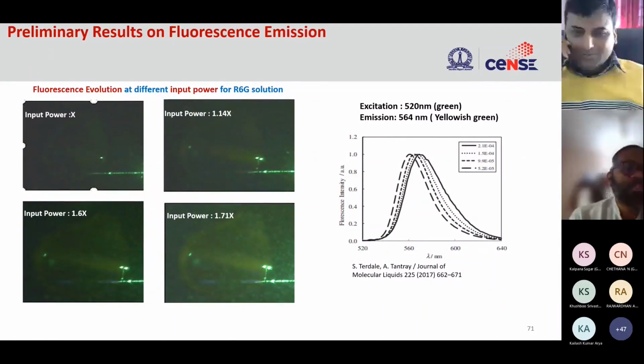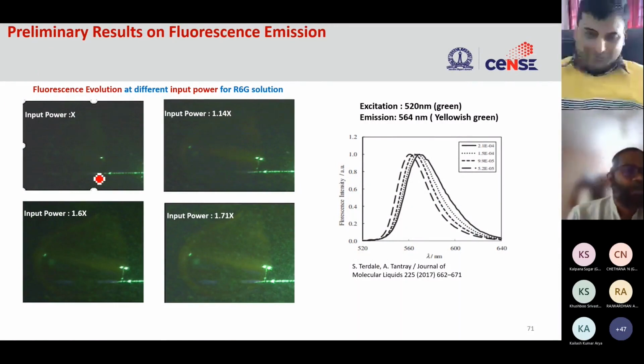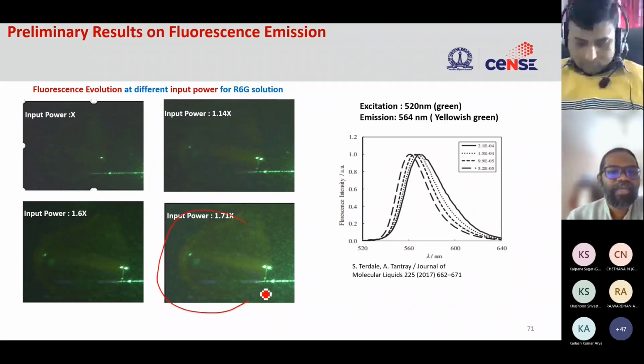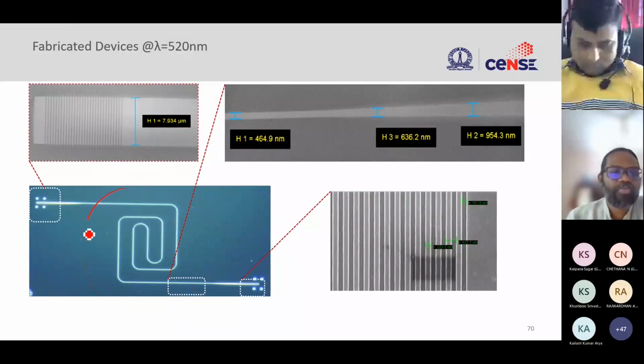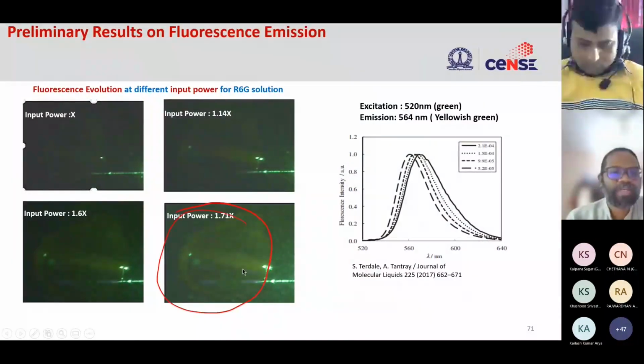We are yet to do the Raman experiment, but this is already old data where we have drop casted a rhodamine 6G solution, which is a fluorescent dye. You can see here a green spot. This green spot is generated from this waveguide. We have drop casted our dye on top of it, and you couple the light in, and the light interacts with the volume, and you can see here generation of fluorescent signals.